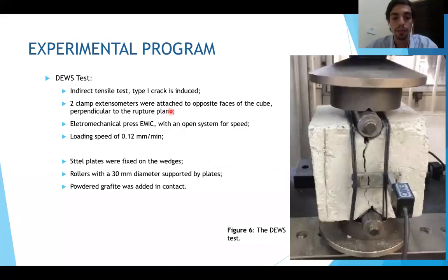After that preparation, the test itself was done. It is an indirect tensile test where a type 1 crack of pure tension is induced, enabling easy analysis. To measure the crack opening, 2 clamp extensometers were attached with elastic on opposite faces of the cube, perpendicular to the crack plane, as can be seen in the photo.